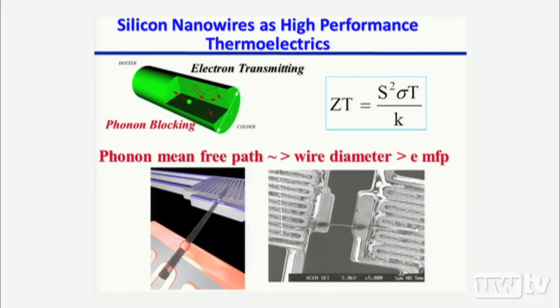For example, in the silicon case, the phonon mean free path is on the order of 200 to 300 nanometers, while the electron mean free path is on the order of a couple of lattice constants, in the nanometer region. So the basic design principle here is you design a nanostructure that bridges those two length scales so that you can block the phonon transport, basically block the thermal transport and reduce the thermal conductivity, while encouraging the electron transport so that the thermal power would be as large as possible. So that's the basic design principle.